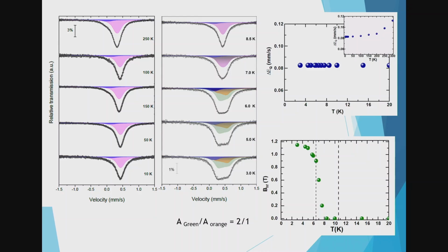Thank you. And the other question is a curiosity only. Did you take a Mossbauer spectrum without iron doping in order to see any contamination of the precursor? Yes, we did with ruthenium, I remember, but I should look up this data somewhere. But we use very pure elements to make these materials, the best elements you can buy in Alfa Aesar. And the content of impurity, I think, is much below the possibility of detection of the technique.